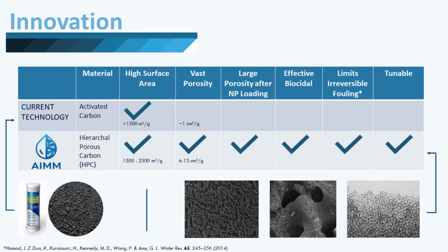This colossal porosity allows for the loading and anchoring of biocidal nanoparticles while still maintaining high porosity, and it's demonstrably been proven to be less prone to irreversible fouling, which means higher water flux for longer. Thus, our HPC filters can provide the simple ease and use of a Brita system with the performance of a water treatment plant.